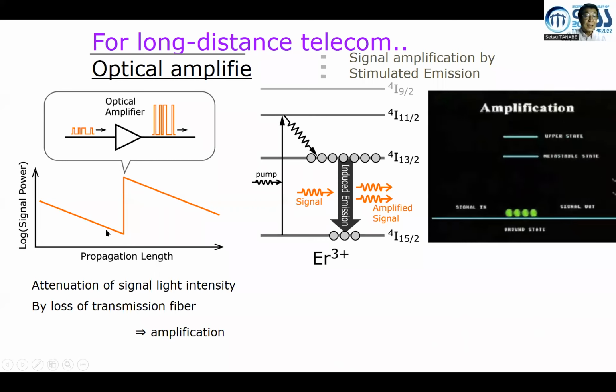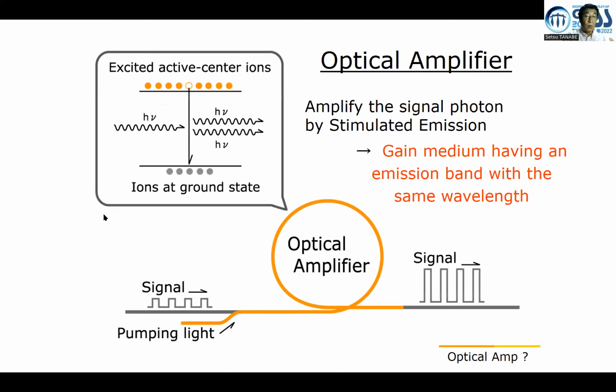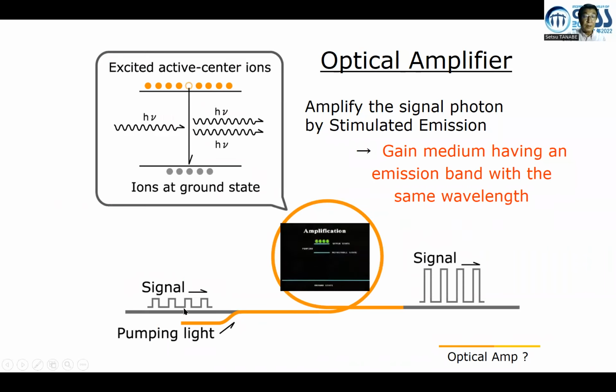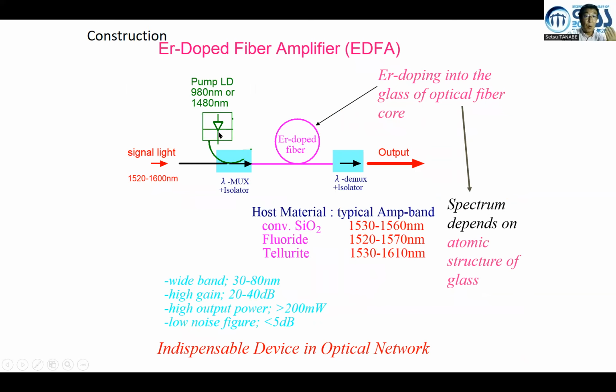The signal decreases exponentially by Rayleigh scattering and several other reasons, but inline optical amplifiers can work to amplify it by 30 dB or 40 dB. So the signal can be amplified in the same phase at the same wavelength, and parallel amplification is also possible, by stimulated emission of erbium-doped glass fiber having a broad emission spectrum. That is pumped through a WDM coupler with a 980 nanometer or 1480 nanometer laser diode, which excites the second and first excited states respectively, to achieve population inversion in erbium ions.